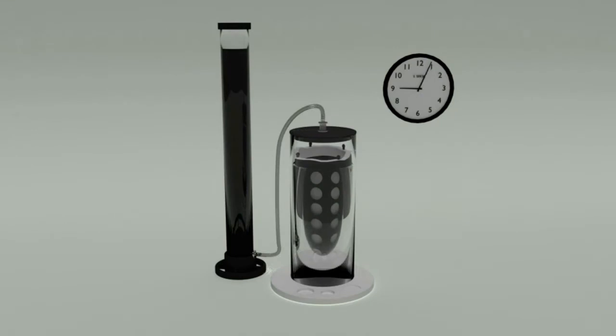Typical dissolving time is about 10 to 30 minutes. However, dissolving time may vary considerably. This is primarily due to temperature. For every decrease in temperature of 20 degrees Fahrenheit, it will take twice as long for the metal to dissolve.